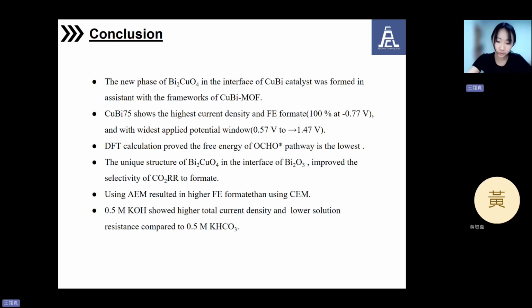So finally, here's the conclusion of our presentation. First, a new phase of Bi2CuO4 was successfully formed at the interface of the CuBi catalyst by the MOF framework. This phase has a crucial role in enhancing the catalytic behavior. Among all tested compositions, CuBi 75 showed the highest current density and higher formate selectivity and maintained a wide applied potential window. DFT calculations further supported this, showing that the OCHO pathway has the lowest free energy barrier, confirmed as the preferred route for formate formation.